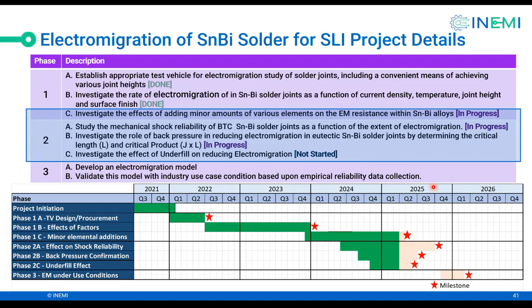2B is investigating the role of the back pressure effect, also called the Blech effect, where if the solder joint gets too thin, the electromigration doesn't occur because of the back pressure developed if there is any bismuth migration. And 2C, there have been a couple of papers recently in the literature which seem to indicate, at least at the first level, that if underfill is there surrounding the joint, the electromigration decreases. So we are trying to confirm that with the BTC solder joint rather than a first level solder joint.